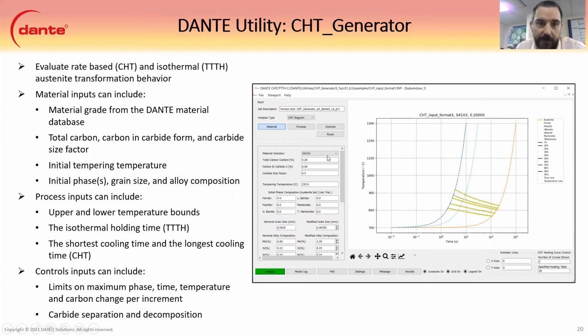You use your material selection. You'd have a prior tempering temperature for your martensite, because that does affect your austenite start. You have your initial phases, which are very important. We'll talk about those in the next couple slides. And your grain size, color composition, same way as the DANTE material database. This will also do carbon and carbides. You can see carbon and carbide A and carbide size factor, because it does carbide dissolution for that rate-based calculation as well. So the controls inputs are a little different for this.